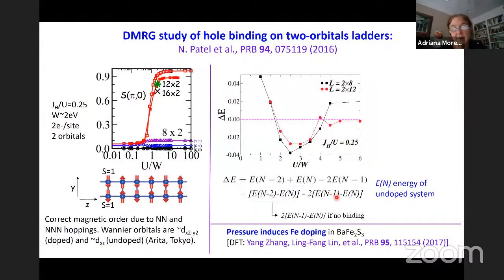With DMRG, we calculate the ground state energy for the parent compound, then the ground state energy for n-1 particles and for n-2 particles, and construct this difference in energy. When this is negative, it means it's energetically more favorable to put the two particles together rather than separately, and that would indicate pairing.